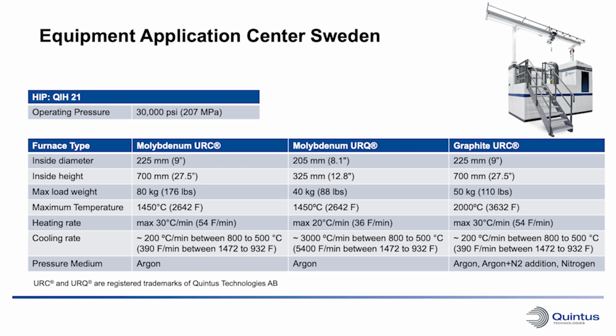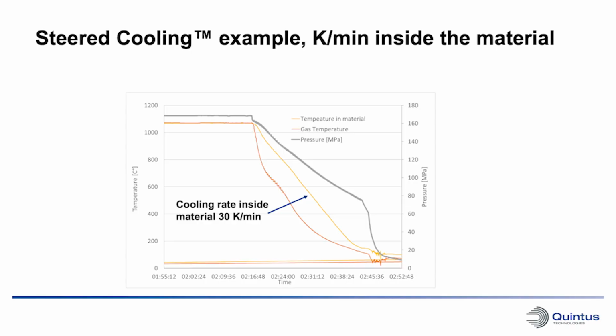We can end up with between 200 and 300 degrees per minute in that one, but actually that's the workhorse for us. We run around 60 to 70% of all our cycles in that furnace. Okay, and the cooling rate of 200 to 300 Kelvin per minute, can you steer that in any way, or is it just free fall? Yeah, that's also one of the benefits with that furnace, that you can steer the cooling sequence. Actually, you have 6 thermocouples in the furnace, and you can use one of them or all of them or just a part of them to control with.